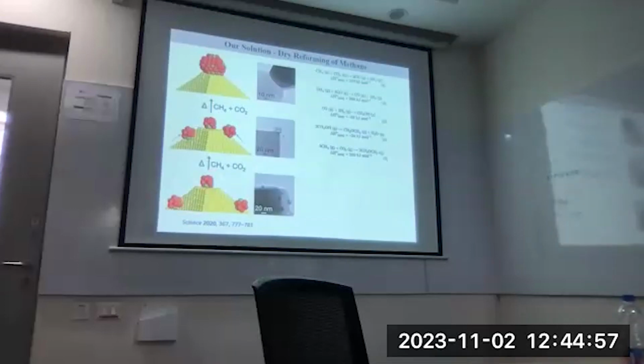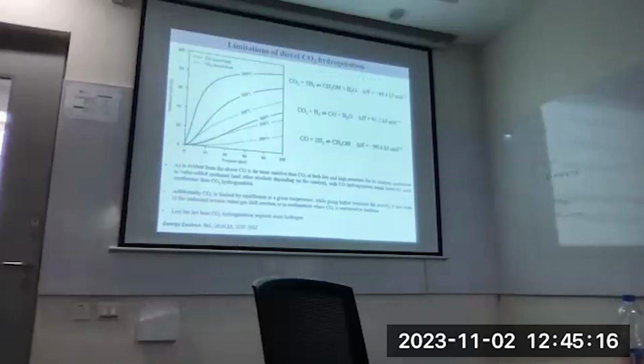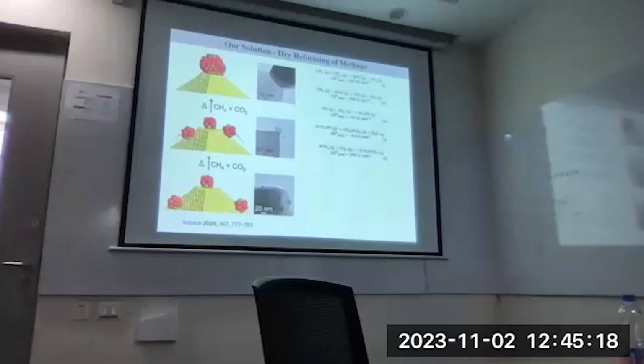In this particular case, the nickel molybdenum nanoparticles go to certain defect edge sites on the magnesium oxide and stabilize at that surface. This nanoparticle efficiently converts CH4 and CO2 into carbon monoxide and hydrogen. You avoid these reactions. There are other reactions which take place, like some coking. Normally in DRM, dry reforming of methane, coking happens. When you give very high temperature to CH4, it forms carbon.